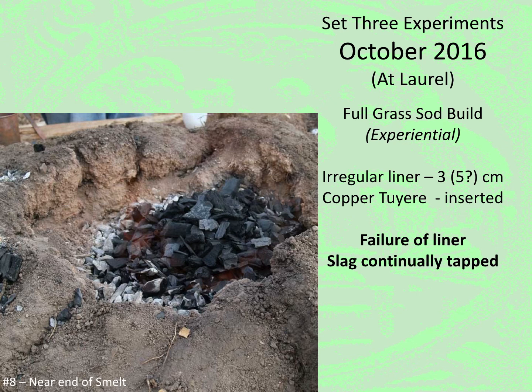The net result of all these aspects was a complete failure of the inner clay liner. This would fill the lower slag room area, not leaving a lot of room for accumulated slag. As a result, slag was continually tapped and modified through the progress of this smelt.